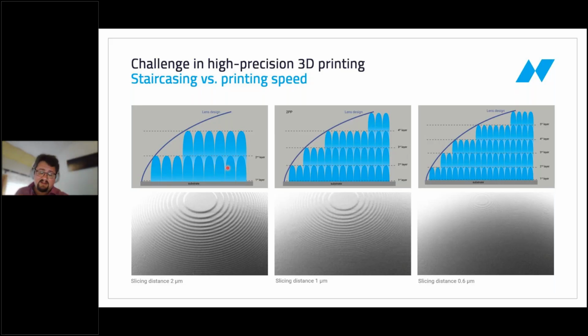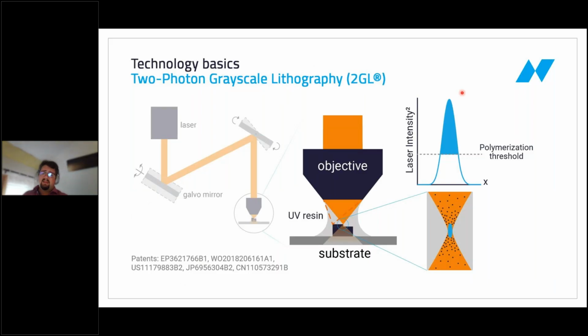And this works great, and we have seen very successful customer applications implemented with this, but it always takes a lot of printing time. So there's this fundamental trade-off: you can go fast, but then you have a very rough surface with lots of discretization artifacts, or you can go slow, but then you can have a smooth surface. This fundamental trade-off we somehow wanted to get around. And this is why we invented two-photon grayscale lithography.